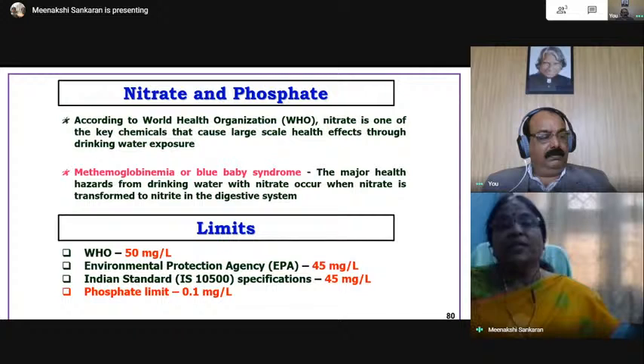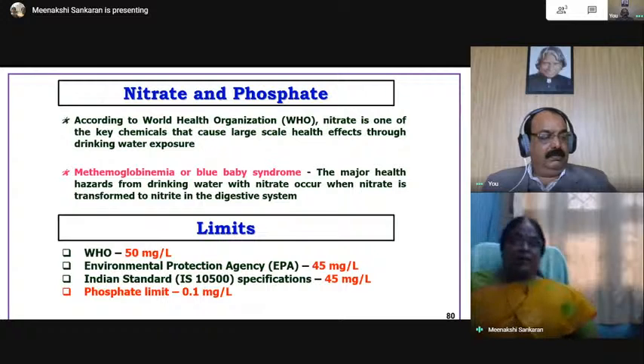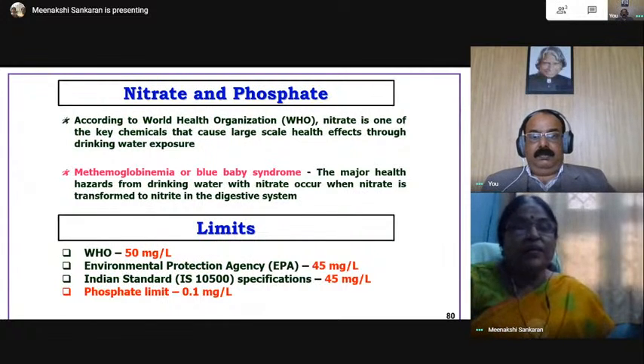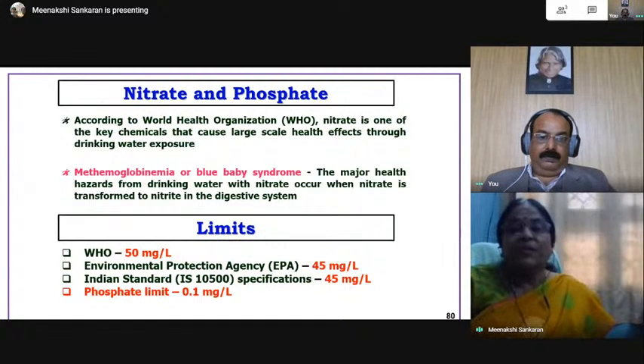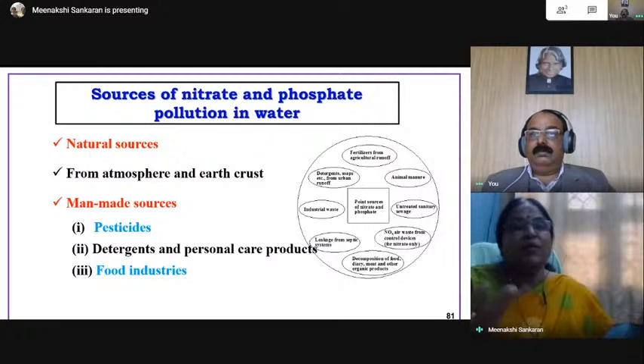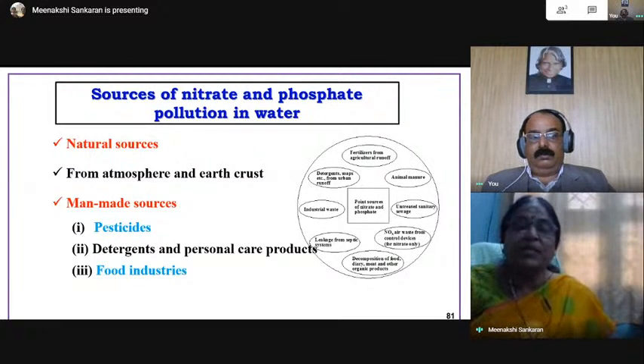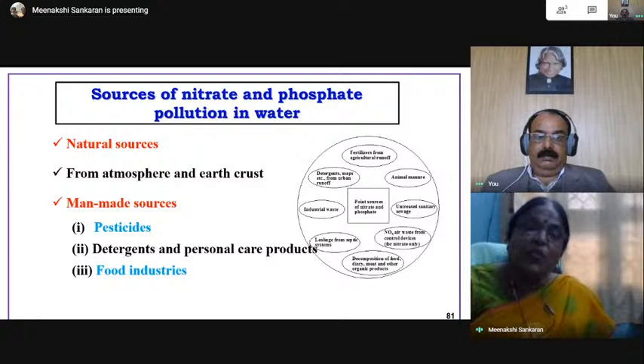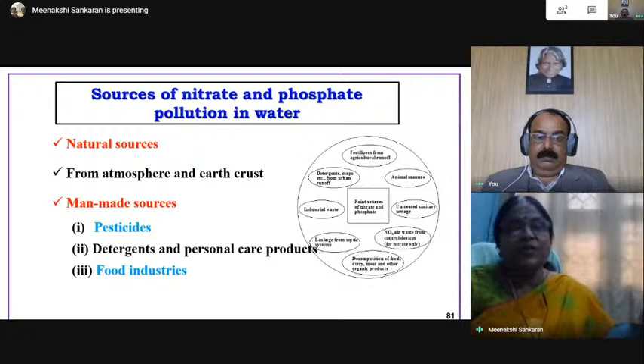According to the World Health Organization, the maximum permissible limit for nitrate has been fixed as 50 milligram per liter, whereas for phosphate it is only 0.1 milligram per liter. We have observed more than 150 milligram per liter for nitrate, and for phosphate we have observed more than 50 milligram per liter. So we have started doing this research for the removal of nitrate and phosphate. Again, the source may be our atmosphere and earth crust, which are found to contain more amounts of nitrogen and phosphate minerals. They are soluble in drinking water, so naturally they will contaminate the water. And among man-made sources, many of the pesticides are found to contain nitrogen and phosphates. Food industries, detergents, and soaps have phosphates. So naturally, they will contaminate the drinking water.